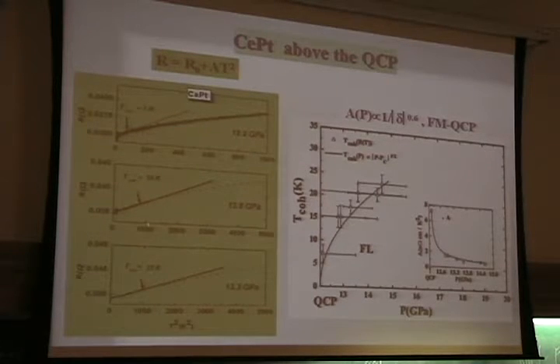So above the quantum critical point, we could follow the coherence line, fitting our resistivity curves, and this is the coherence line. And also we could get the electron-electron coefficient, and you see how it diverges near the quantum critical point. Okay, and the obtained exponent is 0.6. That is, and also the coherence line follows the mean field theory, for which the exponent is 1.5. Okay.